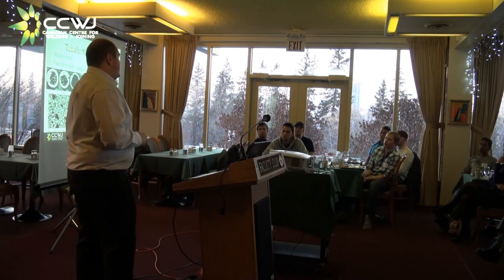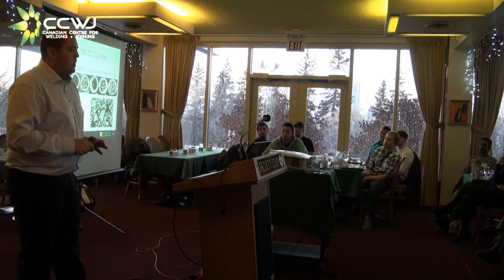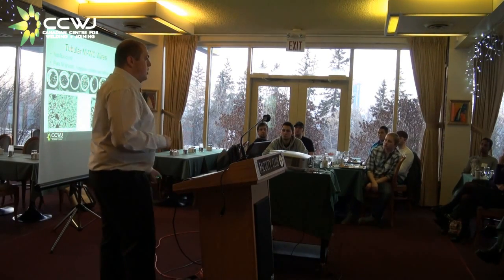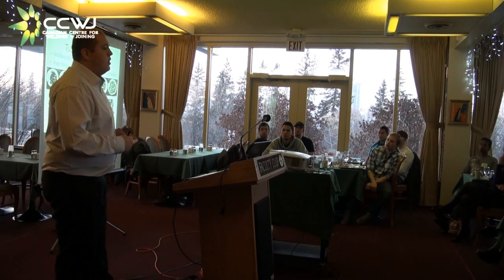One of the things I'm going to focus on a little bit more is the tubular wires themselves. Now, these wires are like chrome carbide wires. There's no AWS spec, so every manufacturer is different. Just because you buy a 1.6 millimeter wire from company A does not mean it's going to be exactly the same thing from company B. Another misconception is that it's called flux core. Well, there's no slag. You don't chip slag off the end. Some people call them metal core. Well, they're not actually metal core because ceramic carbide is not a metal. So we could call it ceramic core or hard core wires.